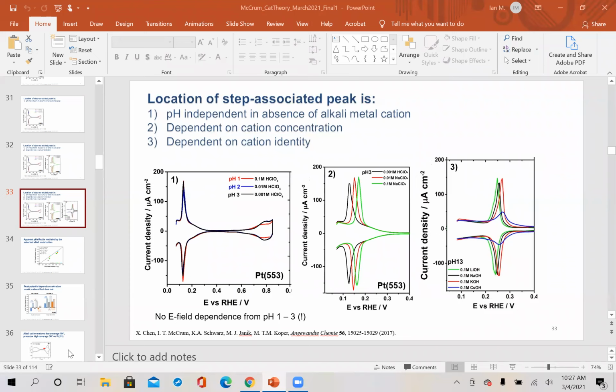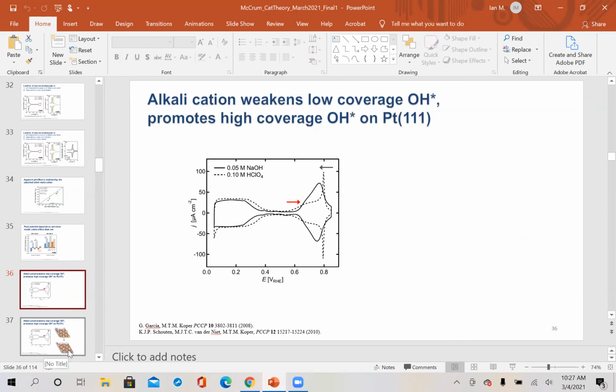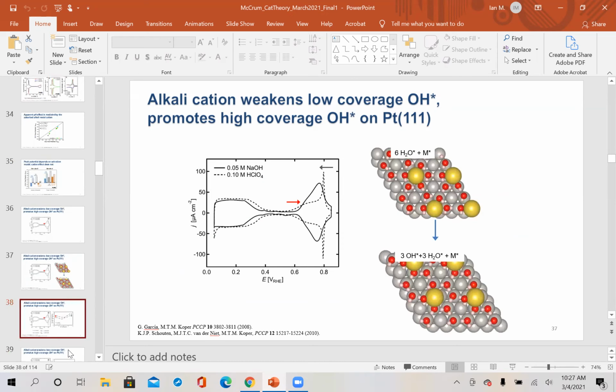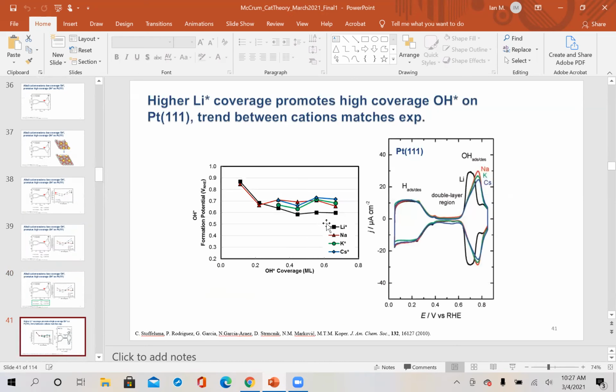I'll add that on the flat surface, we're looking at a one-dimensional kind of interaction, along the line of the step. If we look at the effect of cations on hydroxide on the 2D surface, the 111 surface, and we want to capture the difference between the cations, we need to consider that they can adsorb to different coverages. Now we have to consider that coverage effect on the surface. Lithium can adsorb to a higher coverage. Why? Again, we haven't perfectly pieced that apart. I'm sure it has something to do with the size. Certainly there's a steric hindrance with something like cesium. We simply can't fit a lot of it on the surface and fit OH and water.